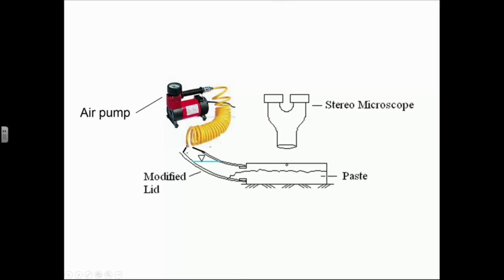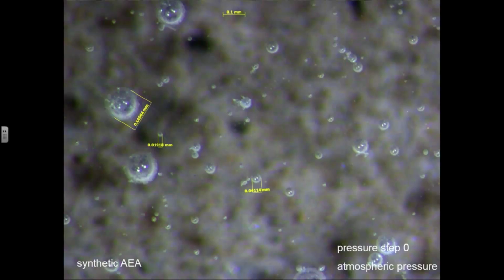And so the data I'm about to show you is not the air void system inside the cement paste. It is not. But it is the air bubbles that were in the cement paste that rose up and were on the surface, and we're able to watch with a stereo microscope, an optical microscope. We have an air pump over here, and we can pressurize it and simulate an air test. So here we go.